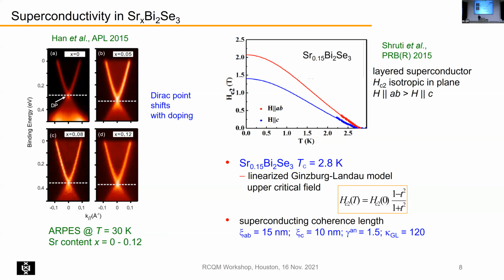Then there was a report about the upper critical field a number of years ago. This group by Shruti measured the upper critical field. This is a layered material, so you can put the field in the plane, and that should be isotropic, or you can put it perpendicular to the layer. So that's what they did. And here are the data. Maybe not so particularly interesting.